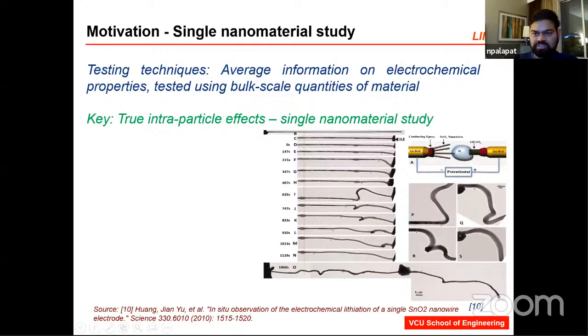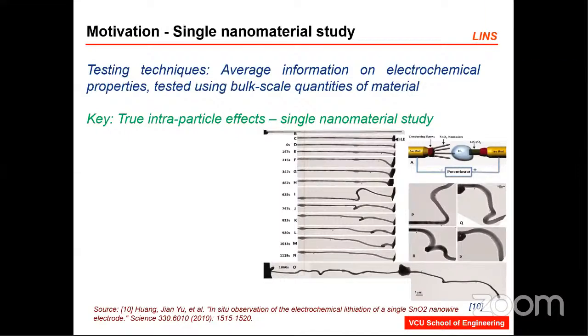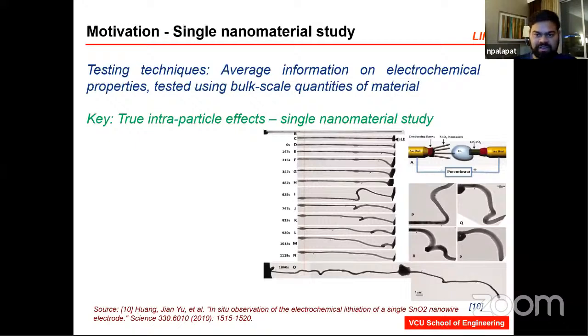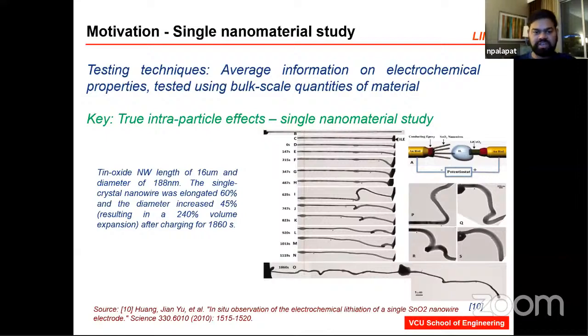This is a transmission electron microscope graph. This is a tin oxide nanowire inside a transmission electron microscope. You have a lithium cobalt oxide cathode, a tin oxide anode, and an ionic electrolyte. Initially, we started charging, performing a similar procedure to a battery where you charge and discharge. Inside the transmission electron microscope, what we observed is, as you see, the length of the nanowire drastically increased, and also the volume of the nanowire increased quite a bit. In exact terms, the diameter increased by about 45%, and the length increased by 60%. So these are some key changes that one can observe when you study a single nanowire at a time.